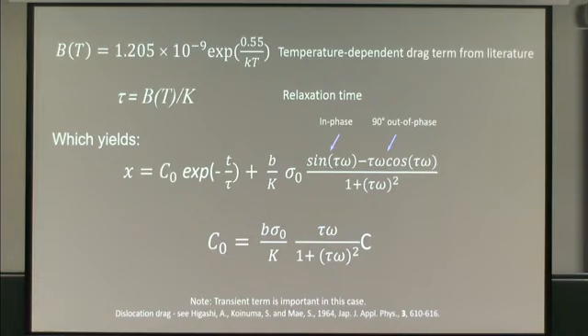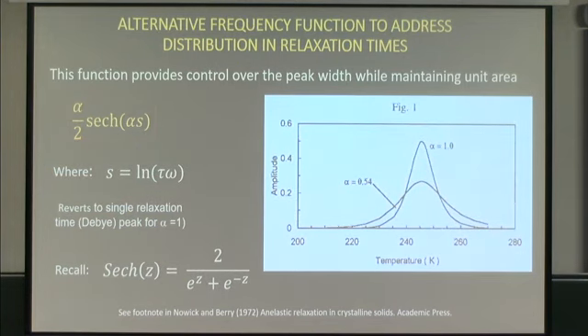You wind up with, so we're still talking about one dislocation here, a transient term that helps you when you're starting from load 0 into a cyclic response. Material scientists will look at in phase and 90 degrees out of phase as the two components of interest. And basically, here's stress, scaled with our trig function. This B over K is basically the loss compliance due to that mechanism. And we'll convert that. Well, actually, we'll do one other thing first. So we start out with a fairly simple solution.